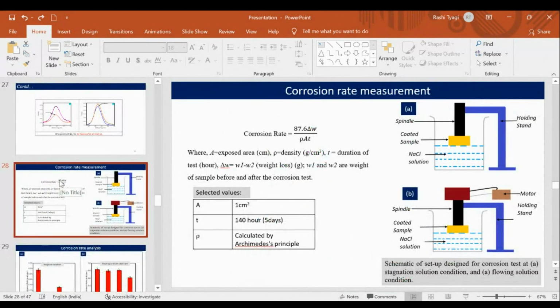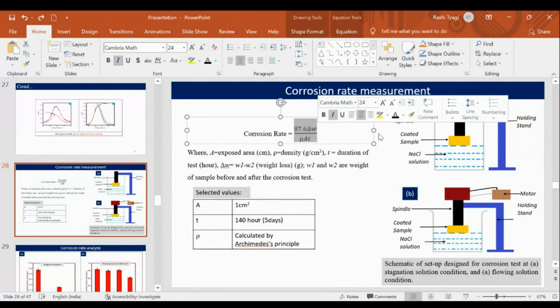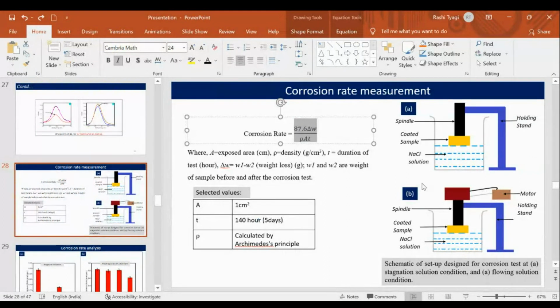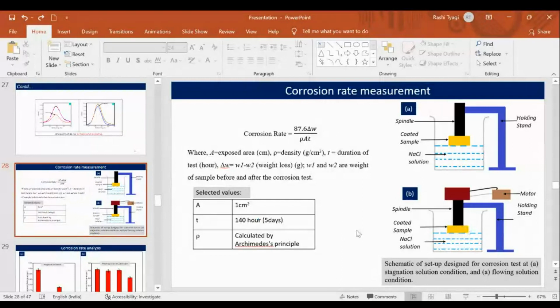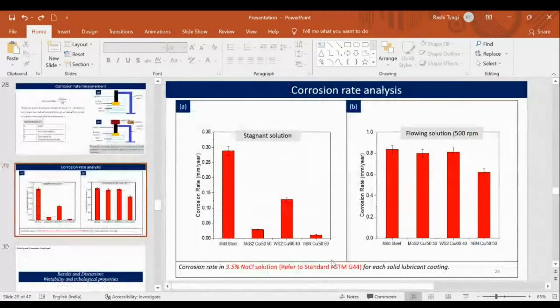Then we have done the corrosion rate measurement. To check whether the coating is corroded or not, we performed a corrosion rate analysis, and this is the formula by which we measured the corrosion rate. It is a weight loss method that we have used. We did the analysis under stagnant solution and flowing water conditions. The water is flowed using a motor. Stagnant water is used to check whether corrosion is affected by the motion of the water.